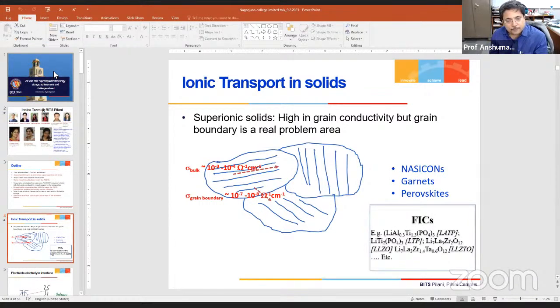then ionic transport is difficult. People have developed, in the last 40, 50 years, various interesting structures inside the solid, so that ionic transport can be made via tunnel-like structures. Using such tunnel-like structures, we can achieve very fast ionic solids. The ionic solid can be comparable nowadays to molten salts and aqueous solutions. As far as in-grain conductivity is concerned, you have NASICONs, garnets, and various other perovskite kind of materials where the conductivity is extremely high, comparable to aqueous solutions and molten salts.